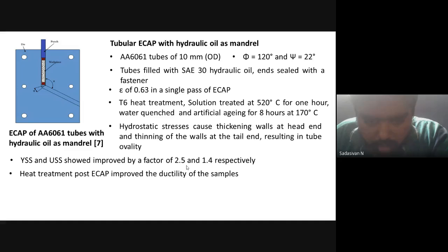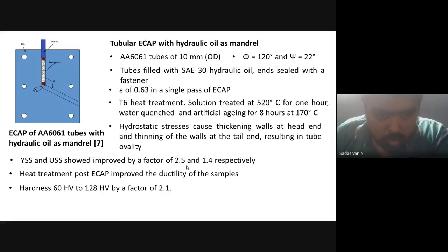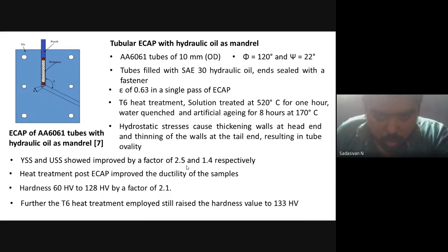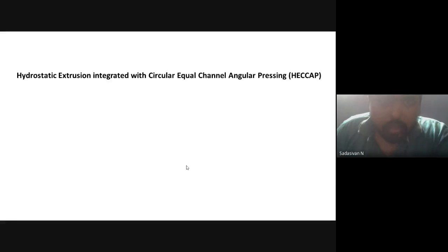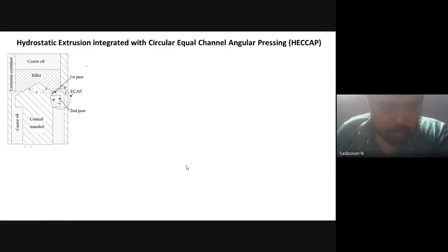Strength is meaningless if you have a very brittle material. Of course, we can improve the strength, but you cannot lose all the ductility. So hardness values improved by a factor of 2.1, that is a 210% improvement. Further improvements were possible after heat treatment, because it is a 6 series alloy, a heat treatable, precipitation hardenable alloy. Next work is...